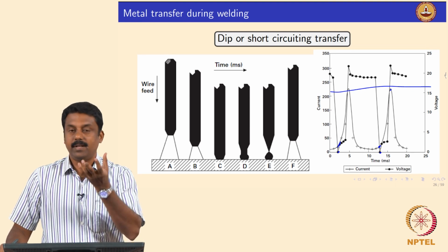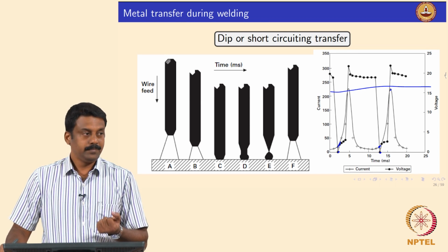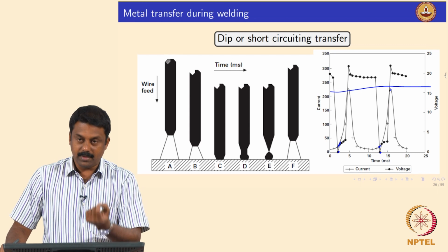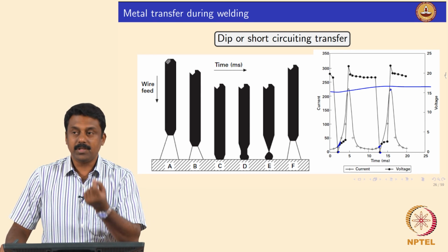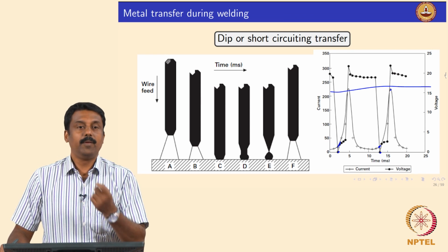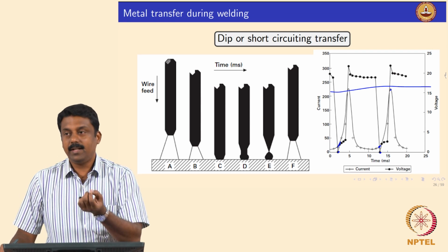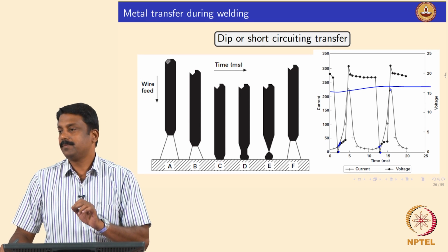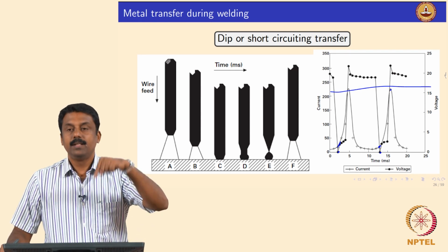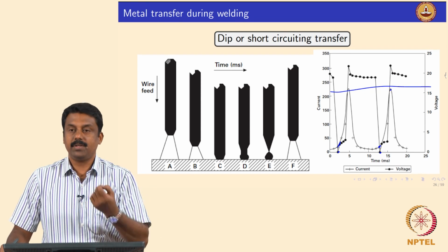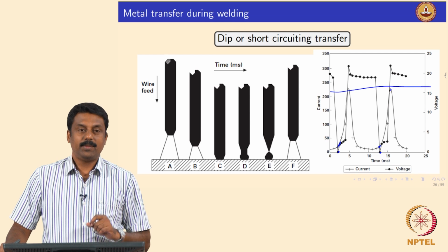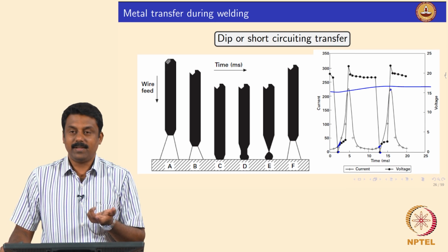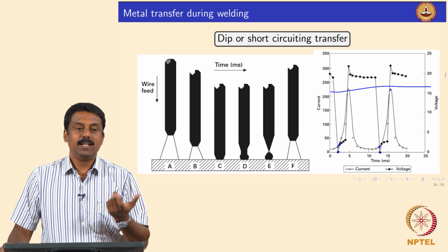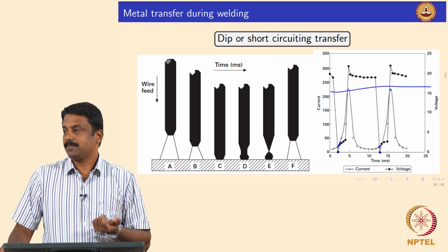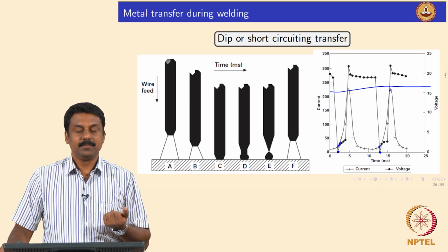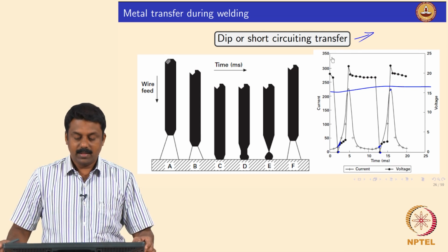So, the droplet is transferred as a superheated liquid in free flight transfer, whereas in the short circuiting transfer, when a droplet is transferred, we also switch off the current. So, when the droplet is transferred, you transfer it close to the melting point of the droplet. Okay. So, the way you are dipping it, the droplet temperature and melting temperature become more or less the same. So, that is why this process is also known as cold metal transfer, because the droplet temperature is much lower than in a conventional droplet transfer. Yes, it is clear. So, this is known as controlled dip short circuiting transfer.